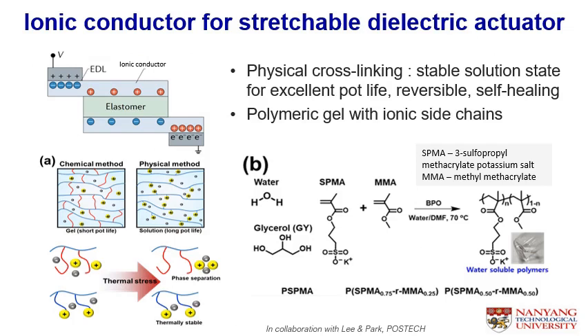The dielectric actuator can also benefit from the modification of the electrode using an ionic conductor. The ionic conductor will create an electric double layer that leads to charge accumulation and therefore enhance strain output. The ionic conductor can be realized using organohydrogel that is prepared based on a physical cross-linking method. This method achieves a stable solution state with an excellent pot life as well as reversible and self-healing ability.